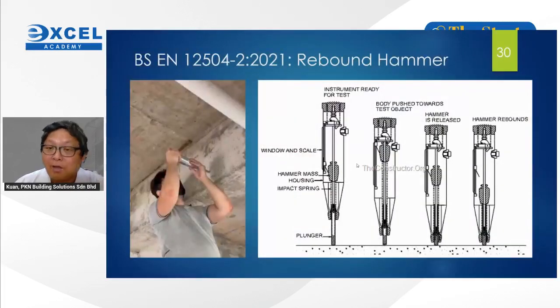And by having all this information, we can know if the rebar is contributing to the loss of the specified strength. And to check compression strength, instead of coring, which is not recommended, we can do in situ testing using a rebound hammer. The issue with the rebound hammer is it always records higher readings than the actual, but the higher reading actually comes from hitting on the area with reinforcement steel bar. So in order to prevent this, we can use a metal detector to locate the position of the reinforcement steel bar. Then we hit our rebound hammer on the area without reinforcement steel bar. Then it will produce a much more reliable record.